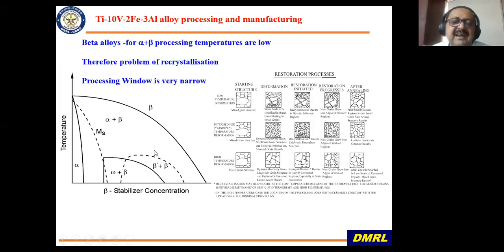Again, beta alloys are slightly difficult and challenging to process because the processing window is very narrow, because beta transus temperature is lower since you have added more stabilizers. So the processing window gets narrower, and you have to hit the right window of deformation as well as temperature to get the uniform structure. If you are either lower or higher, you will get a non-uniform kind of microstructure in your material. So that is where you have to be very careful.